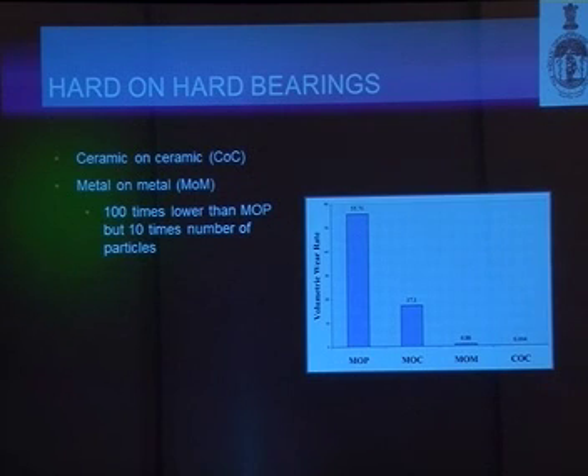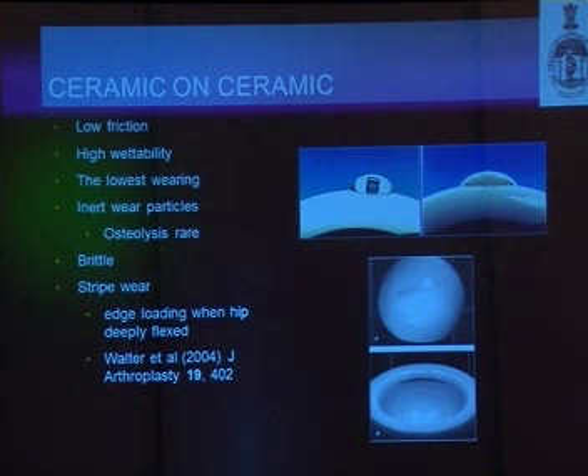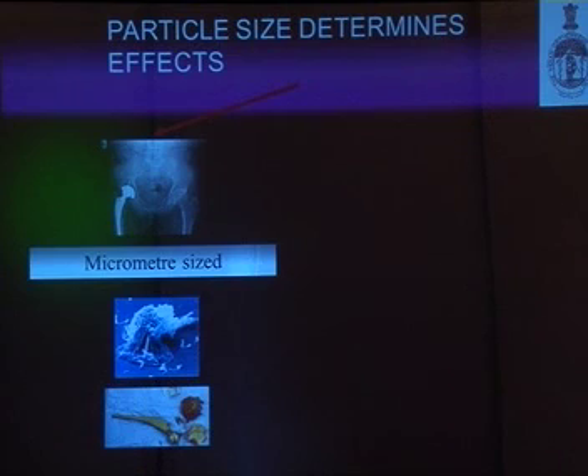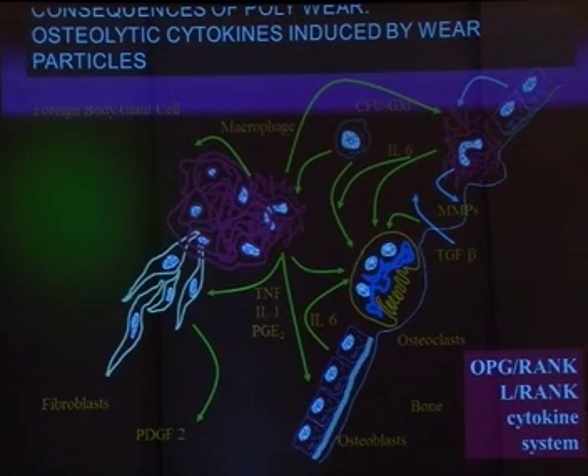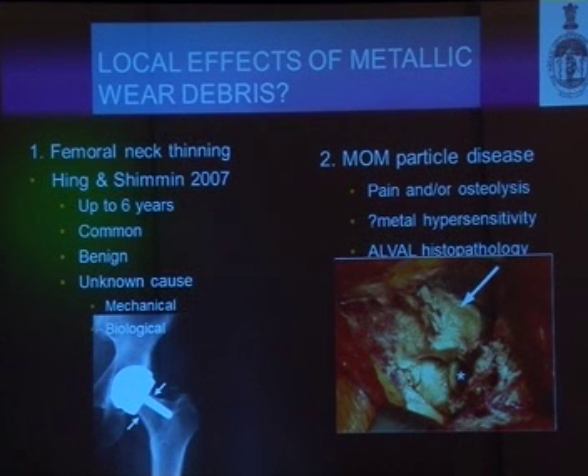We have hard on hard bearings, ceramic on ceramic or metal on metal. The ceramic on ceramic bearing surfaces allow low friction, high wettability, the lowest bearing wear rates, inert particles which don't cause osteolysis as we saw earlier. However, it's brittle and causes stripe wear and edge loading when the hip is deeply flexed. We know the particle sizes determine its effects. If it's micrometer sized, rather than a metal or poly articulation, it causes osteolysis as shown in this cascade. Of course, it also causes femoral neck thinning in a metal on metal articulation as shown by Hing and Shimmin in 2007, or a particle disease which is also known as ALVAL.